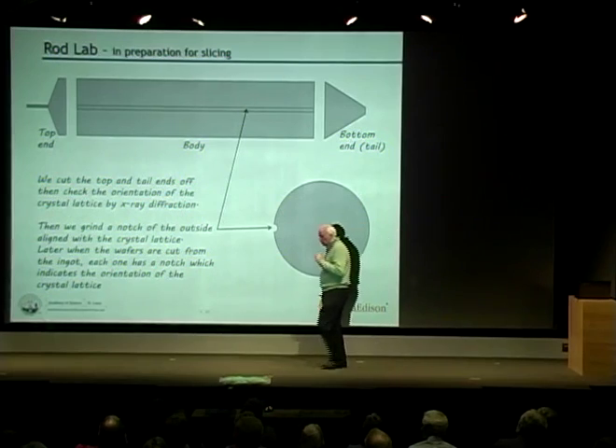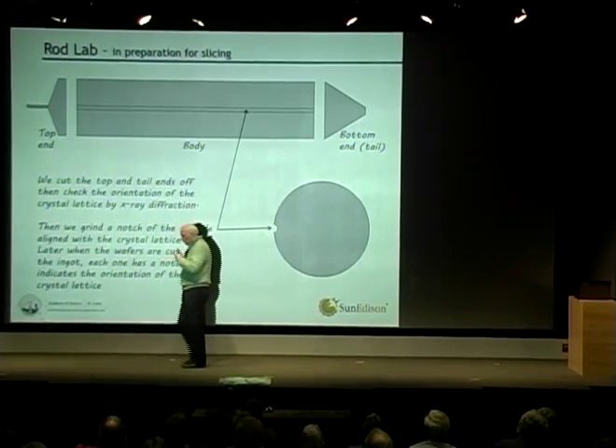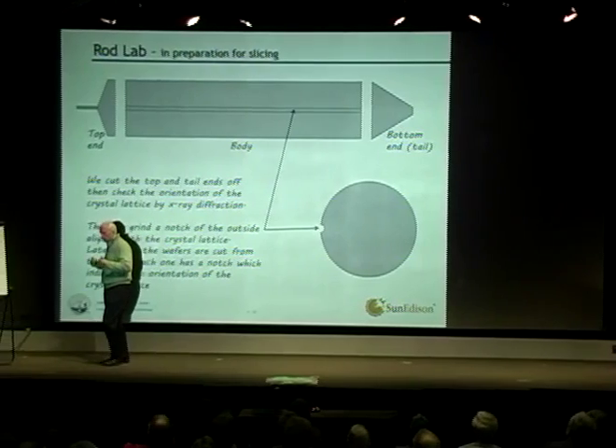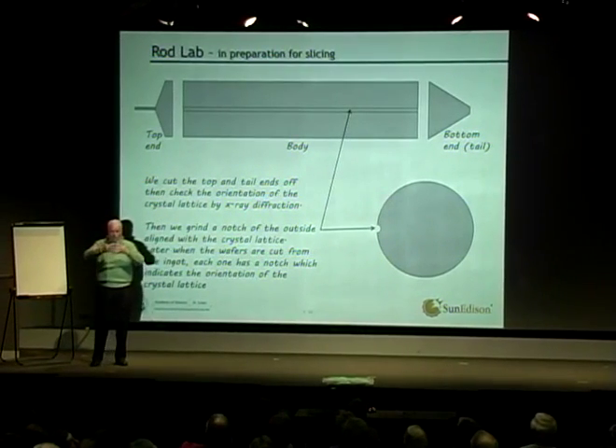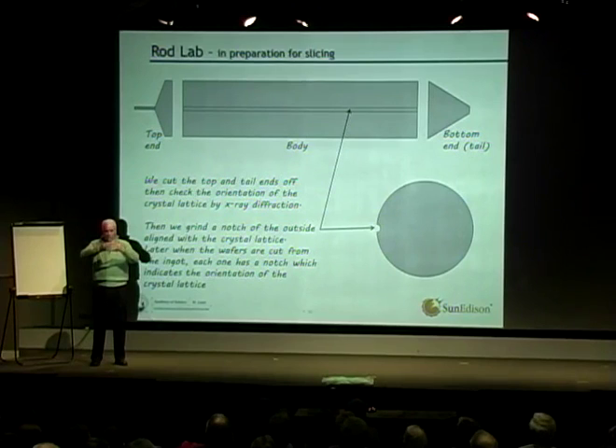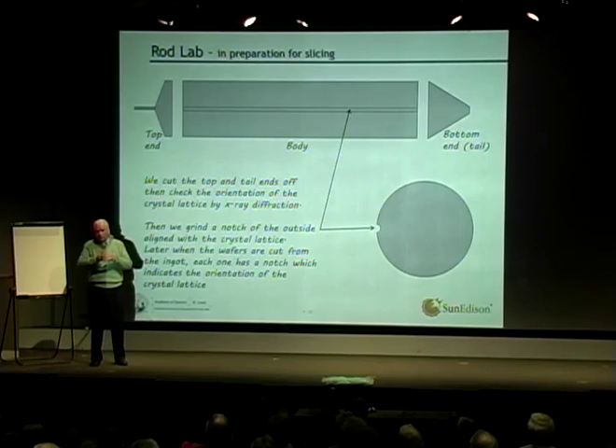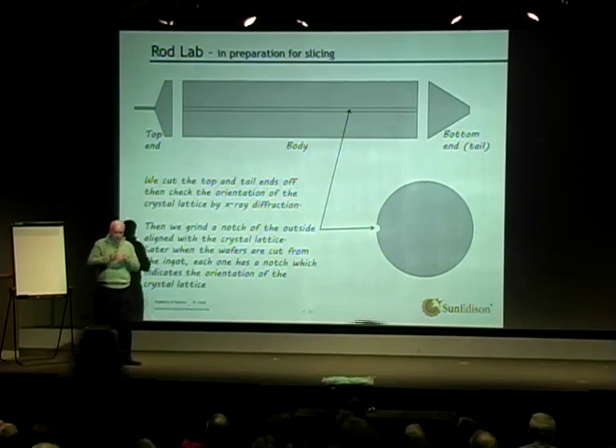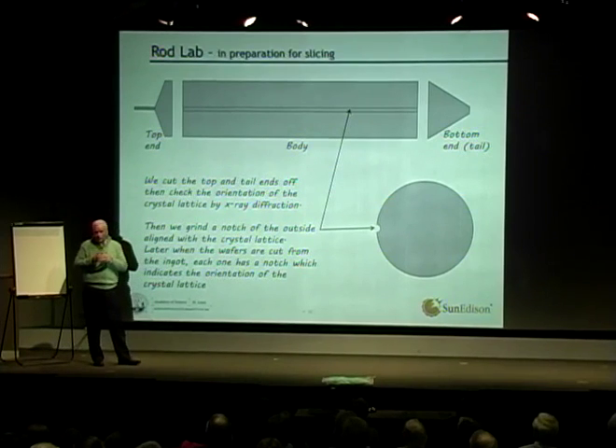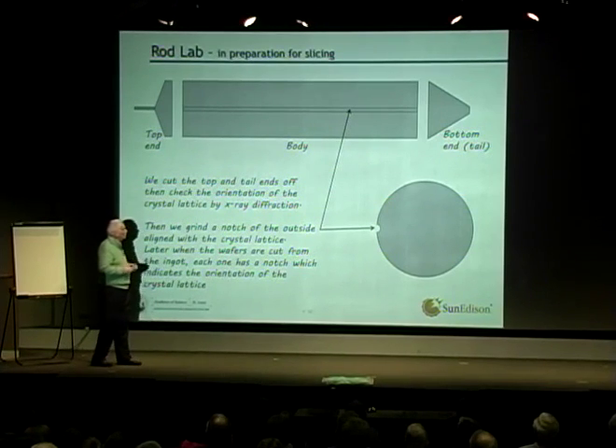And that means in that crystal, all the atoms line up where they're supposed to line up. There's a defect called a dislocation. Now, imagine, so here are my fingers. The atoms are supposed to line up on planes or something like that. If there's a dislocation, this happens. That's what happens when you do a lot of crystal growth under normal conditions, but when we grow a silicon crystal, none of that goes on. Everything's lined up. It's dislocation free. Very important when you're trying to make integrated circuits on the material.